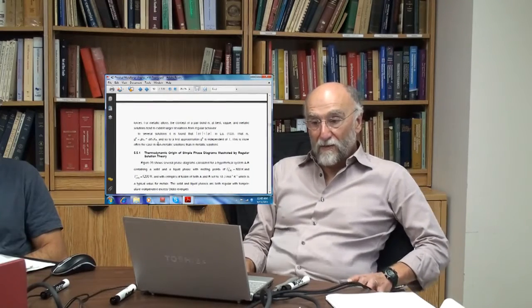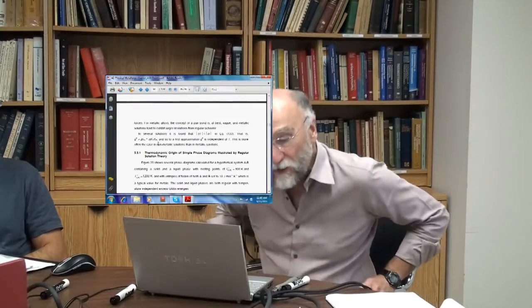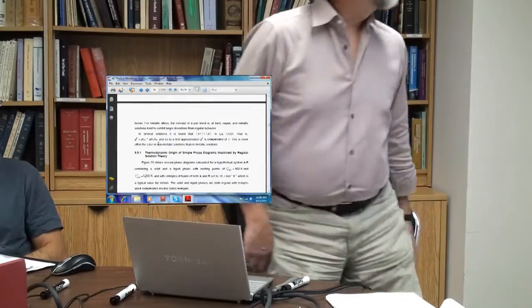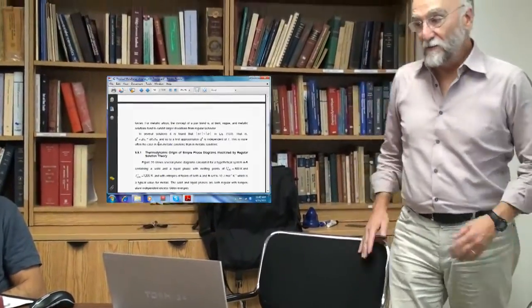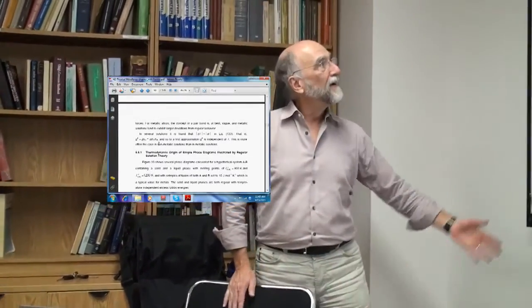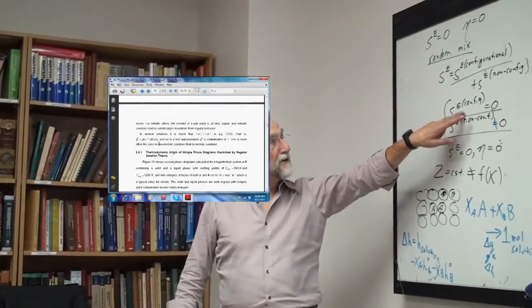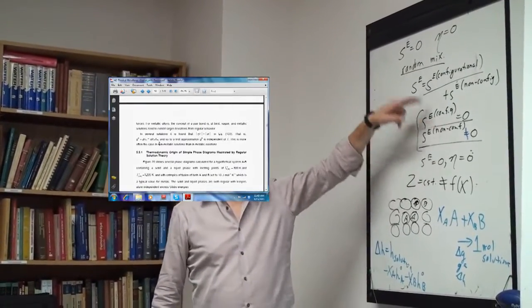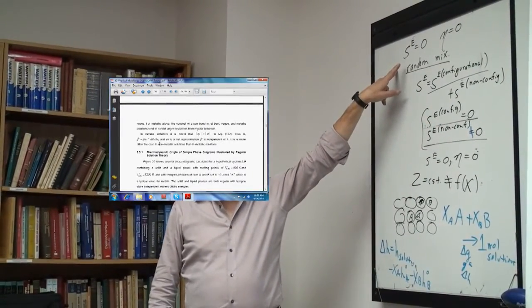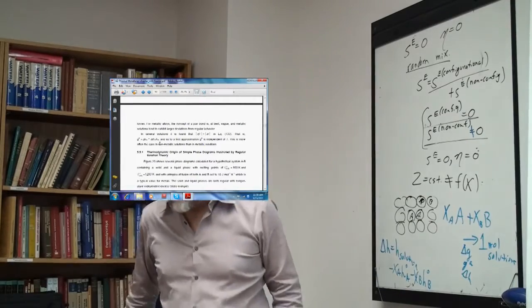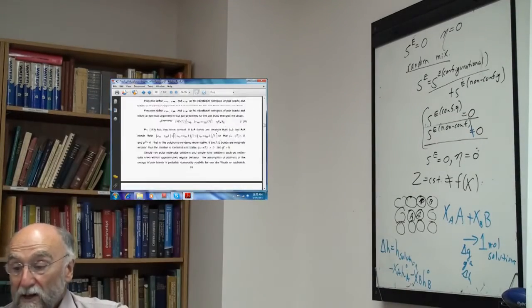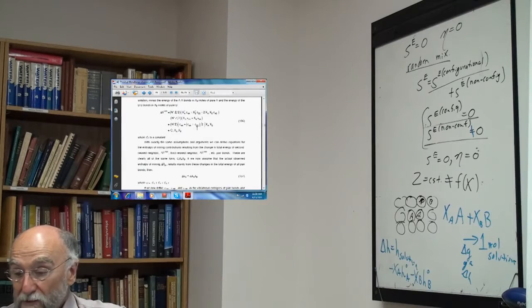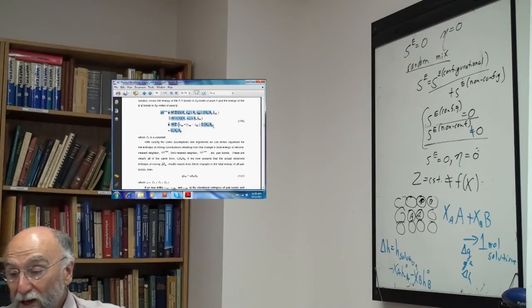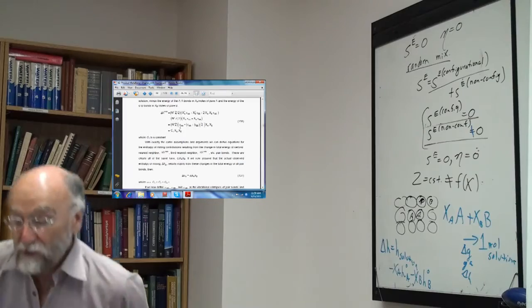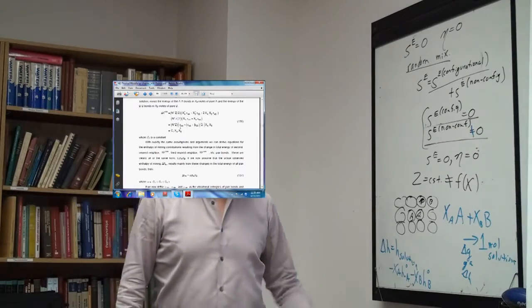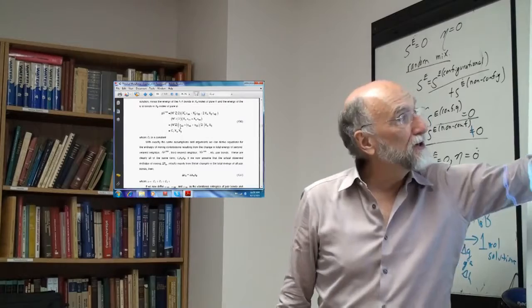Okay, now to get ahead of myself a couple of weeks, when we get into things like the quasi-chemical model, the regular solution model has a fundamental logical flaw. You're saying that the excess configurational entropy is 0, so it's randomly mixed, but then you have a heat that's not 0. Okay, well, let's suppose the delta H is negative. If the delta H is negative, remember that's epsilon AB, it's because this term is not 0. That is, the AB bonds are stronger than the AA and BB bonds.